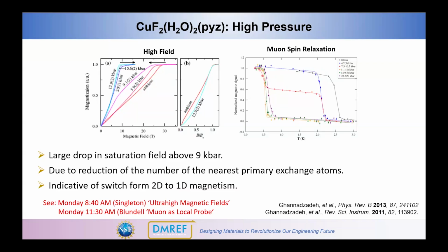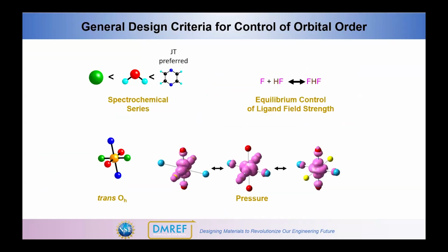And again, I don't have time for this right now, but I did want to call out this one slide that describes the characterization of this copper fluoride hydrate pyrazine coordination polymer, both at high fields and by using muon spin relaxation, because there are 2 talks also in this conference, the one at 8:40 tomorrow morning by John Singleton on ultra high magnetic fields, and the one by Steve Blundell on Monday at 11:30, I think, of the same session using muons as a local probe. And so I would encourage you to listen to those talks as well.